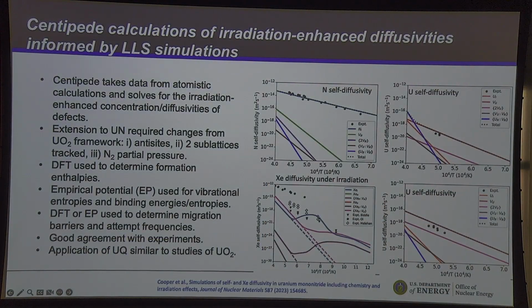So this is a validation step again. There are separate effects kind of tests. You look at some diffusion behavior, experimental data compared to predictions as a function of chemical conditions and which species contributes to it. All that matters here is these points are fairly close to the predicted line. So we have enough confidence that we're doing a decent job. As you see here, decent job, not a perfect job.